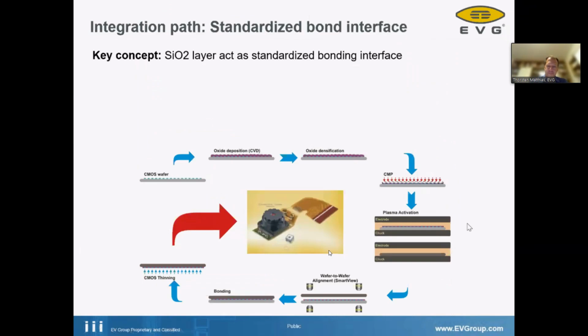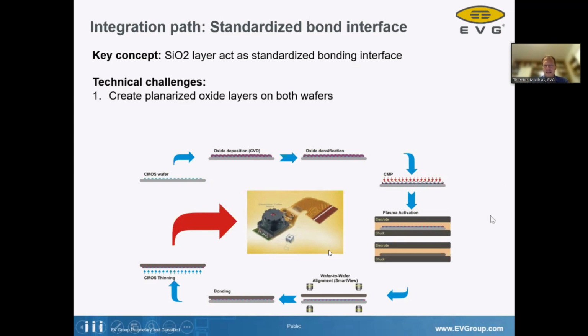And the trick we are basically applying here, or the process we are using, is a so-called fusion bonding process. We are using oxide layers, oxide films on both wafers. These oxide films are planarized, so I apply a process called chemical mechanical polishing to have super flat surfaces. And then once I have oxide layers on both wafers, I can have a very simple, easy bond process. It's void-free, it's very high alignment, it's very fast.